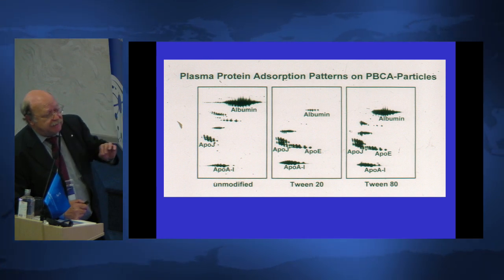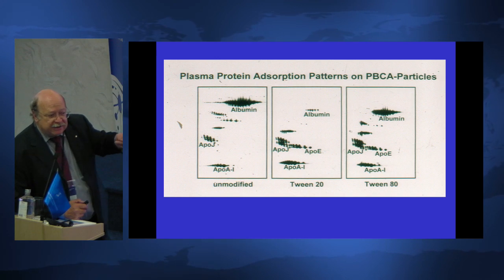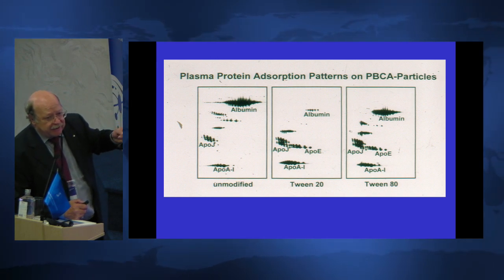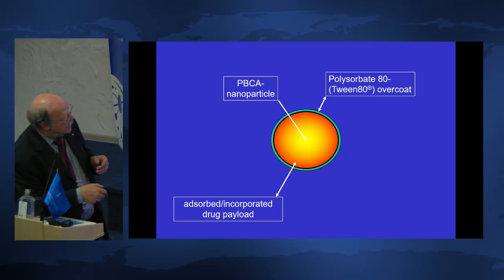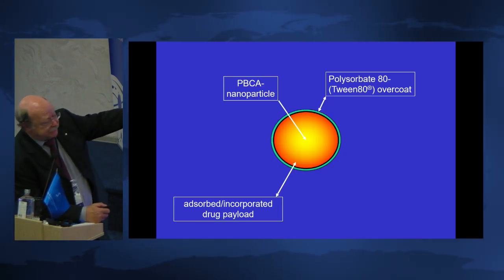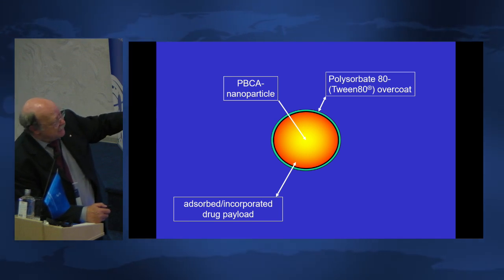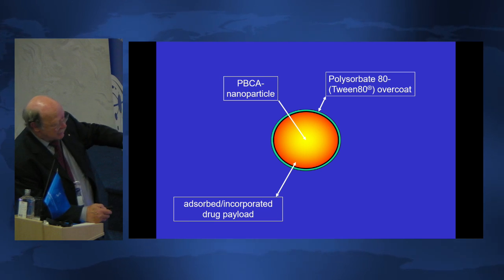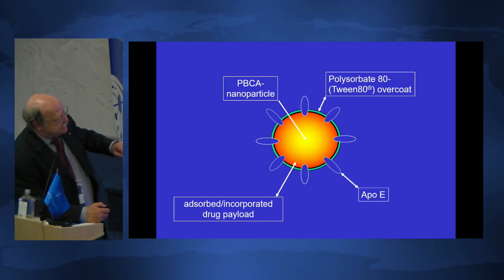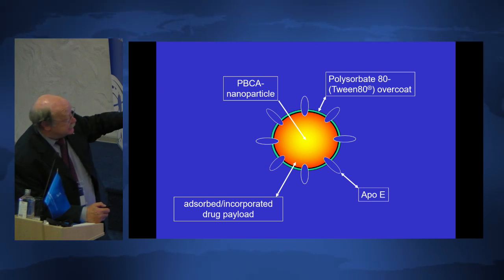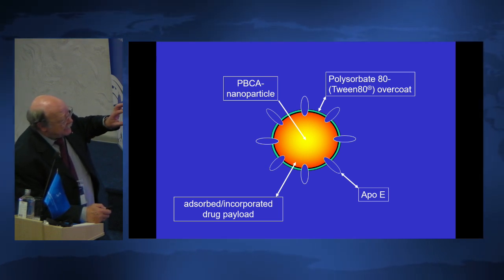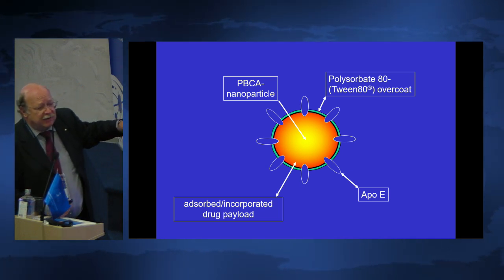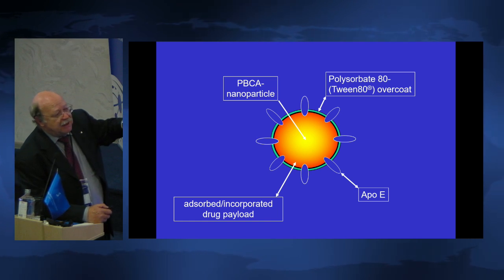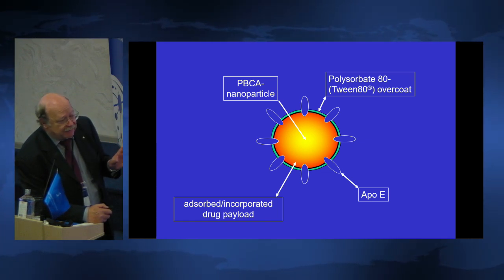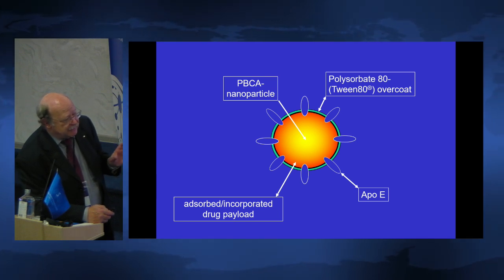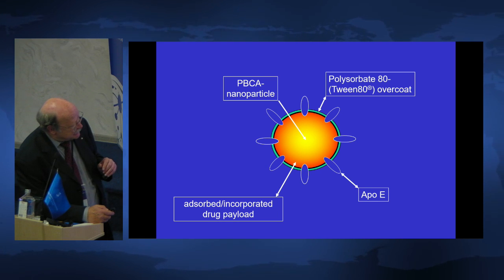Also, the ApoA1 patch was increased. The amount of ApoA1 bound to the nanoparticles was significantly increased. Well, what is happening? Due to this coating, you saw this slide already before, of the polysorbate 80 overcoat, ApoE or also ApoA1 is adsorbed on the surface of the nanoparticles, and then we are addressing, we have identified the receptor in the case of ApoE, the LRP1 receptor. In the case of A1, it seems to be the scavenger receptor that we address.